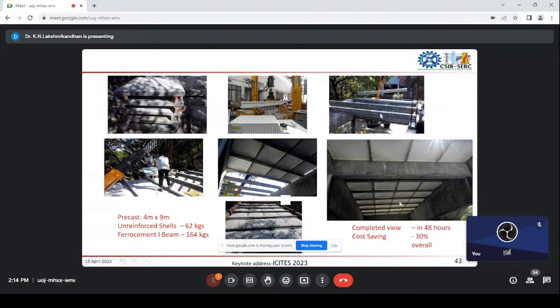You can see the total cost saving we are getting here is 30%, and the total scaffolding requirement is completely eliminated. There is only one problem we see during erection. If there is any sudden accidental load, like an impact, because the shell is unreinforced, a careless action during erection will create a catastrophic failure, and the shell will entirely fail within a few seconds.